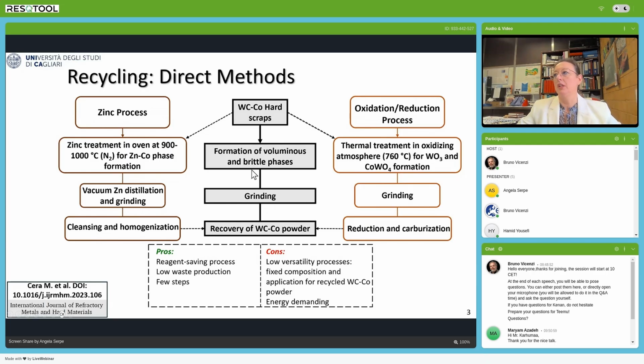The approach is to form voluminous and brittle phases that can be grinded, thus providing a new powder that contains the same amount of cobalt and tungsten as the starting material. So the pros is that this kind of process does not involve chemicals in its production, and also does not produce wastewater at the end of the process. Of course, they involve a few steps for obtaining a material that can have properties closer to the ones of the raw materials.